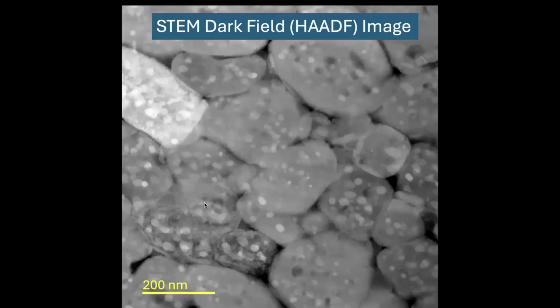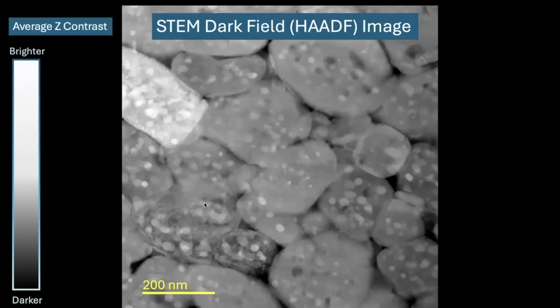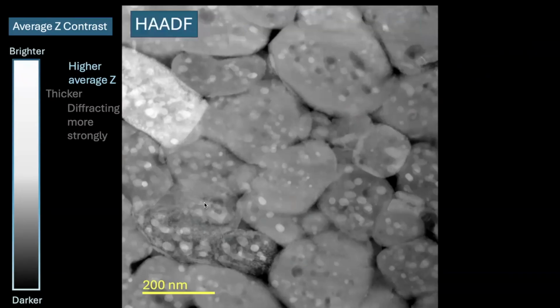So here's a STEM dark field. This is a HAADF image. Here, it's mostly average atomic number contrast. So brighter is higher average atomic number. There's also some contributions from thickness and diffraction. So these will be HAADF images. So let's go through the first sample.